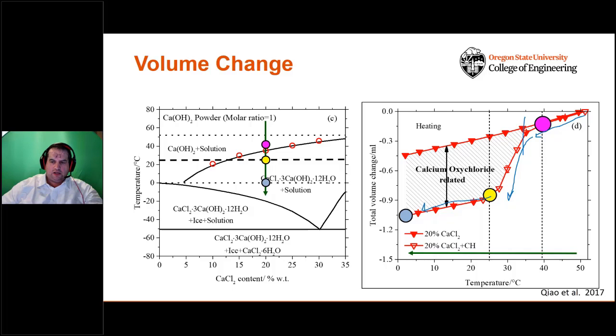Then we see this expansion again. As we heat the material up, we see all of a sudden that we get this oxychloride now re-emerging and essentially becoming much larger. And what's happened is it's deposited in spaces where it really can't just expand freely. Now it causes pressure. Now it causes damage, and now you have a big problem.